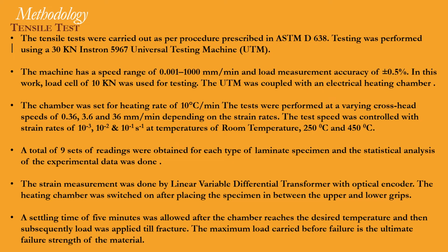The chamber was set for a heating rate of 10 degrees Celsius per minute. The tests were performed at varying crosshead speeds of 0.36, 3.6 and 36 mm per minute depending on the strain rates. The test speed was controlled with strain rates of 10^-3, 10^-2, 10^-1 per second at temperatures of room temperature, 250 degrees Celsius and 450 degrees Celsius. A total of 9 sets of readings were obtained for each type of laminate specimen and the statistical analysis of the experimental data was done. The strain measurement was done by linear variable differential transformer with optical encoder.